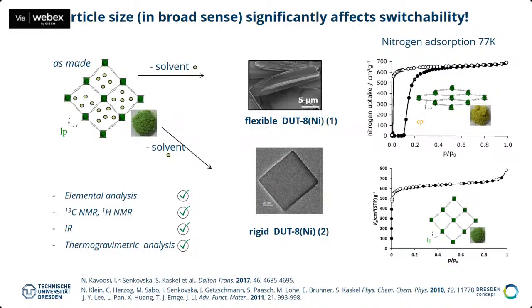In the beginning, we were also not so sure what the reason was, or if there's a different amount of DABCO inside or something like this. But based on our methods, we checked elemental analysis and NMR and so on, and they have all the same composition, but they show completely different isotherms. So this one is basically a pure rigid one, and only the large crystals show the responsivity in this case, and only they show the pore opening and the pore closing.